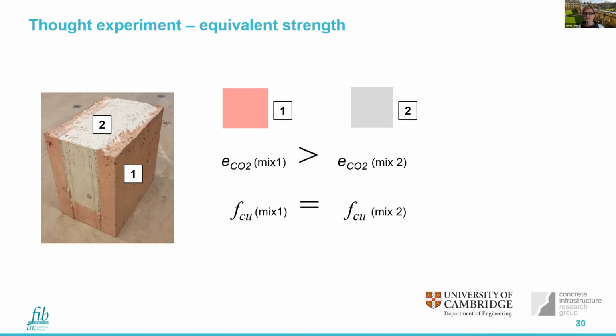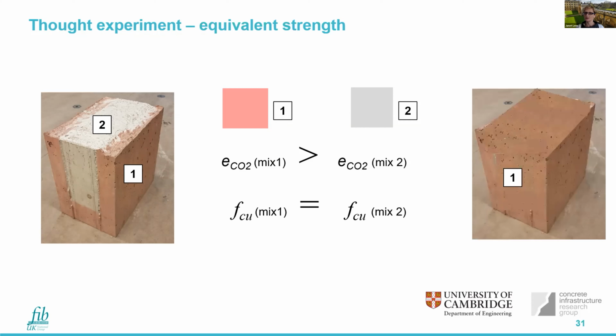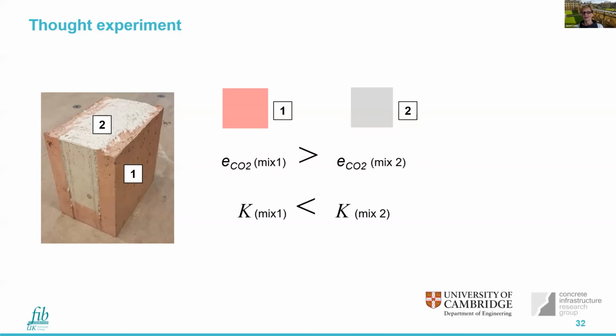So let's say we selected those two mixes and they have the same 28-day cube strength. Are we comfortable with the fact that on a performance equivalent strength basis, that would be the same performance, say, as a cube with a single material, say mix 1? Okay, and next thought experiment, again, ECO2 of mix 1 higher than ECO2 of mix 2. What if we now bring in a carbonation resistance? So let's say the carbonation resistance, i.e. lower K, is better for the pinky mix than the gray mix.